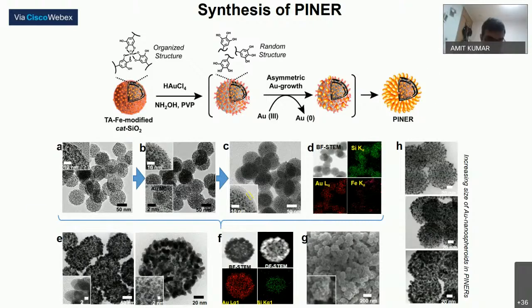We have characterized the final structure. As you can see, the outside periphery is functionalized with the larger gold branches, but inside, I don't know whether you can see it, very tiny gold nanocrystals are modified into the interior of these nanostructures. The size of the plasmonic corona can be well controlled with the dose of gold chloride. The structure was well characterized by TEM, STEM, and elemental mapping.